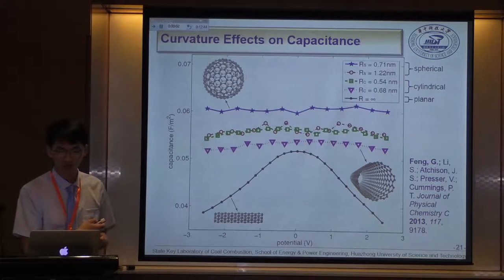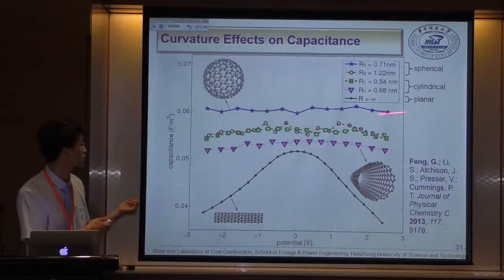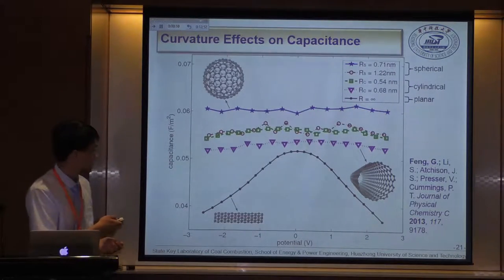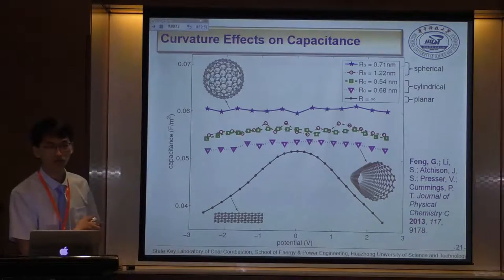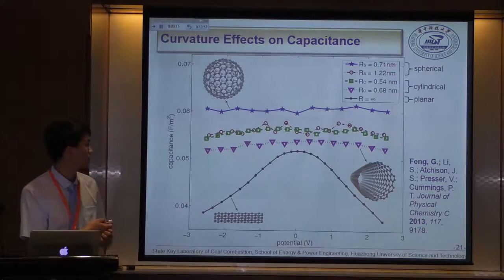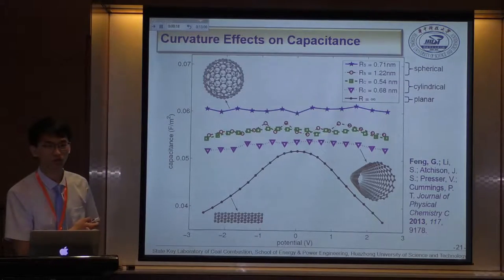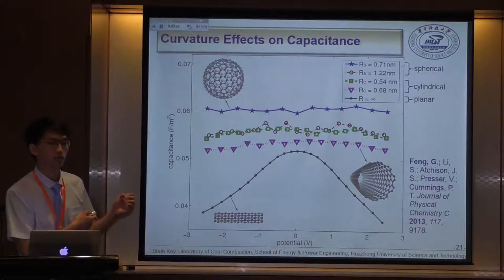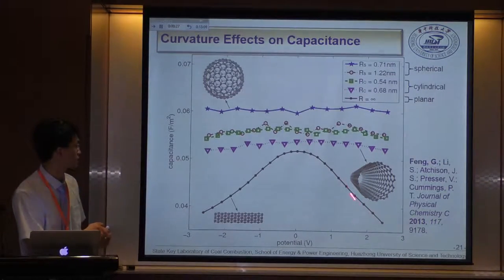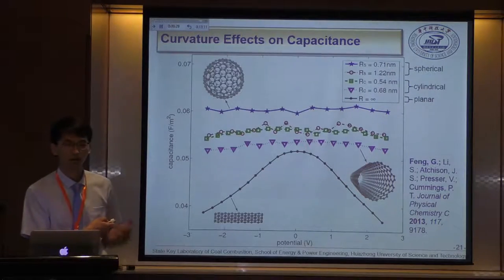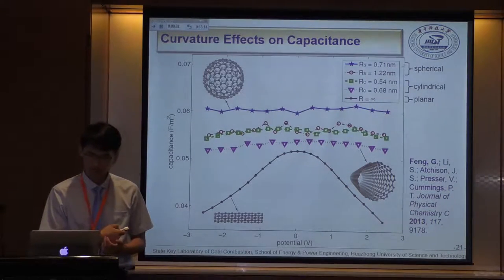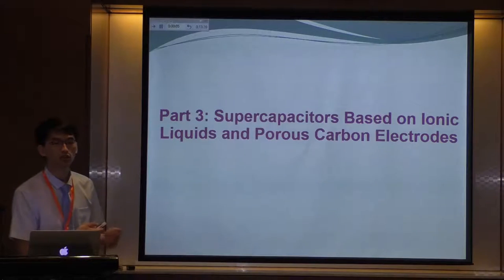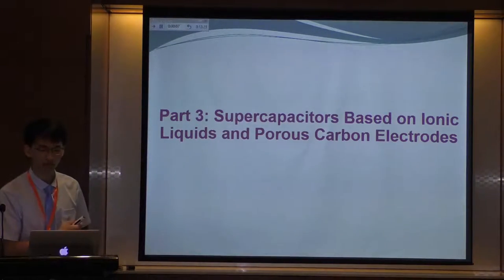We also studied the effect of cylindrical curvature, and the phenomenon is actually the same as described before. If the curvature is within the nanoscale, you will have a flat differential capacitance versus potential curve, which is dramatically different from the planar case. This represents fundamental understanding of supercapacitor behavior.